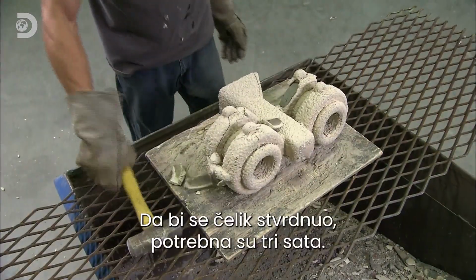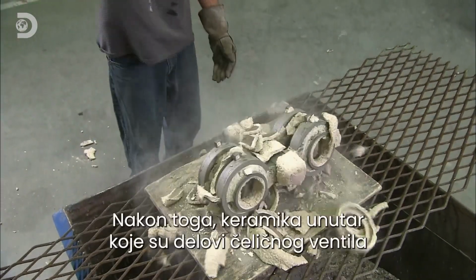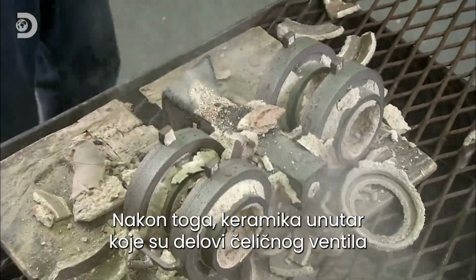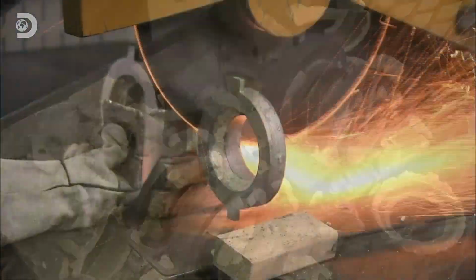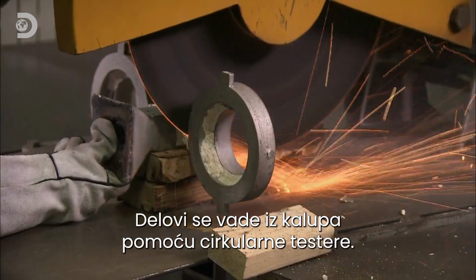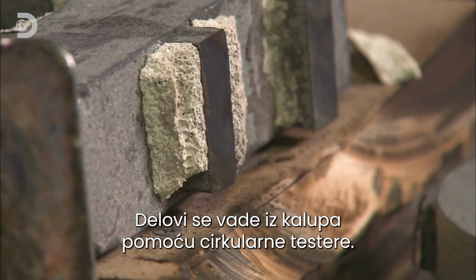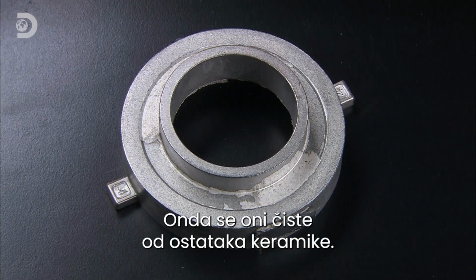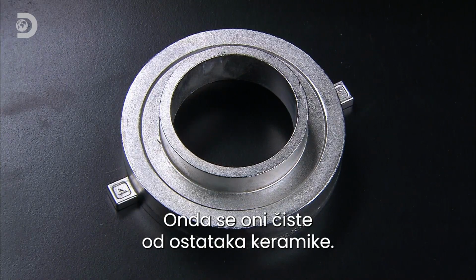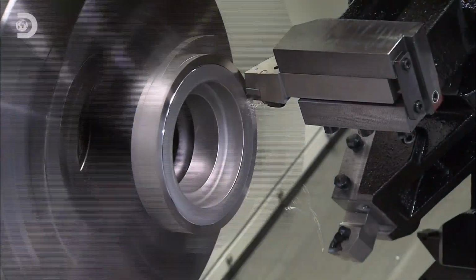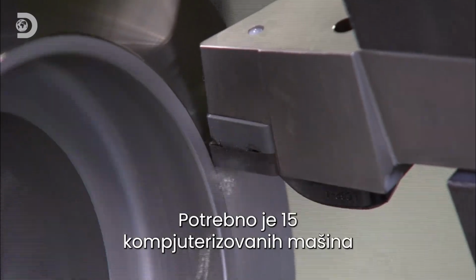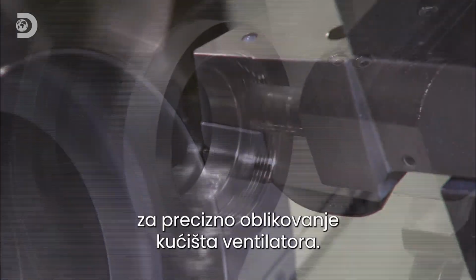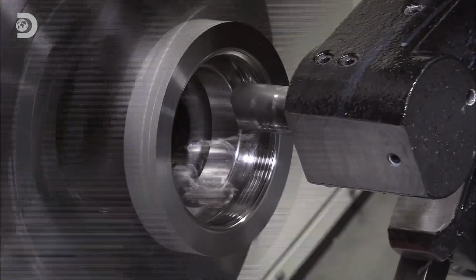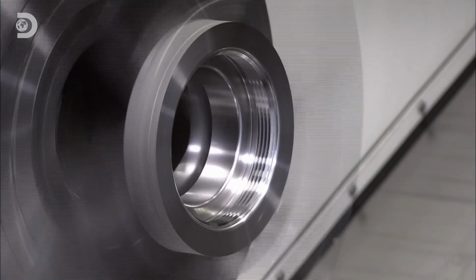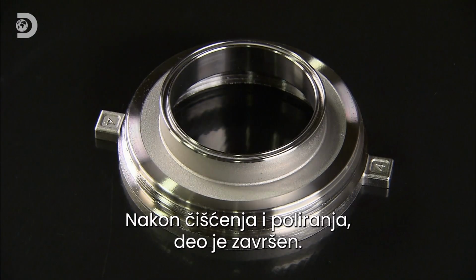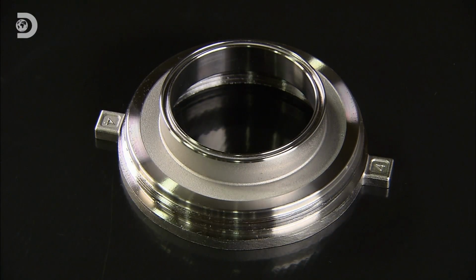It takes 3 hours for the steel to solidify, after which the ceramic can be shattered to reveal the steel vent housing parts. The parts are removed from the tree using a circular saw, before any ceramic residue is cleaned off. 15 computer-driven tools are required to machine the pressure vent housing part to precise measurements. After cleaning and polishing, the part is complete.